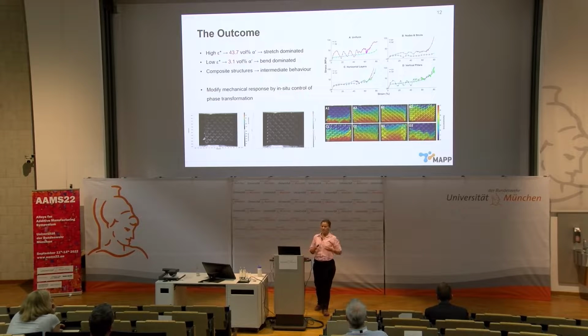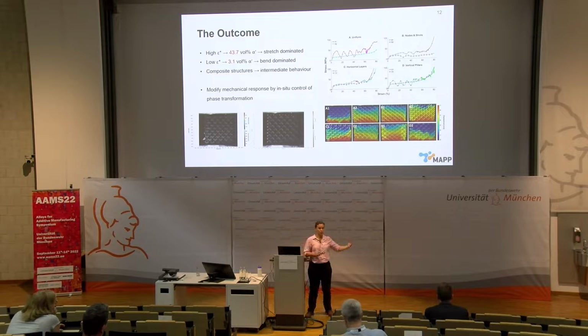So what this is telling us is that through this control of build parameters, with an intentional way of factoring in how much strain we're putting into different regions of the lattice, we're then able to control what phases we produce, and by controlling what phases we produce in a spatially distributed way, we can go on to produce composite structures where we've designed in specific microstructures in specific locations, and with that modify the mechanical response.